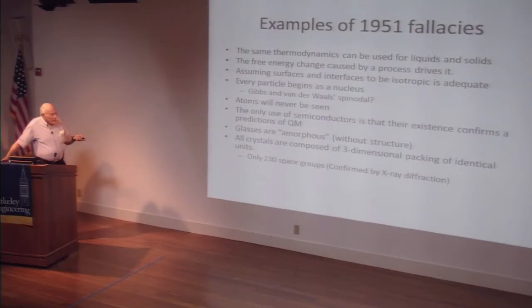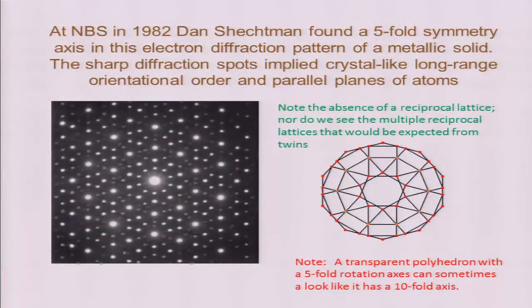So glasses are amorphous without structure. I'll talk a little bit about that. And of course, that still was very much part of the belief that all the crystals are of a packing of. Well, here's what happened. Dan Schechtman, working with us on our rapid solidification project, found five-fold symmetry. This is the original diffraction pattern. It looks like a tenfold, but note that a transparent polyhedron with a five-fold rotation axis will sometimes look like a tenfold axis, so that's what happens.